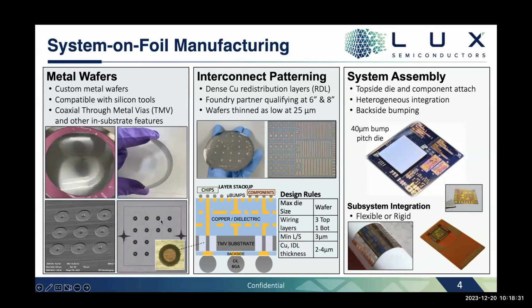Once these patterned metal wafers are complete, they then go into a semiconductor process fab in the back end of the line to receive copper SiO2 interconnects, just like a silicon wafer would go in to receive the interposer interconnects. We've run a number of wafers for various projects and customers. Right now we do 4-inch at Cornell. They have a nanofab there that we use. And we're starting to transition this process to a commercial foundry at both 6 and 8-inch. This is just one example of the wafer that we ran. This is a 3 routing layer wafer, so a patterned substrate with 3 routing layers of copper and dielectric on top of that.